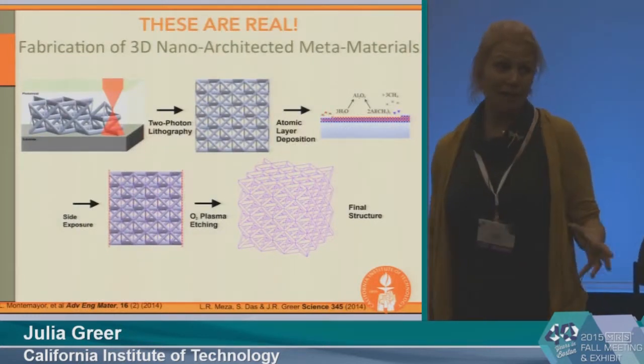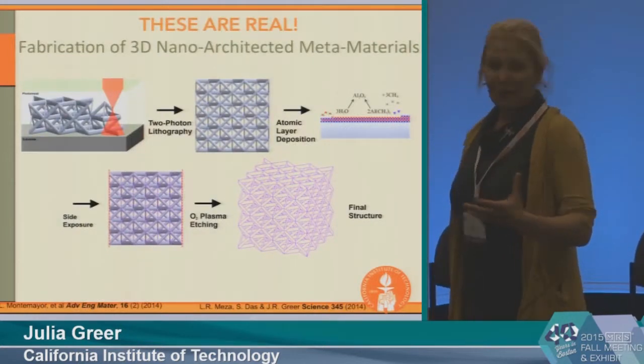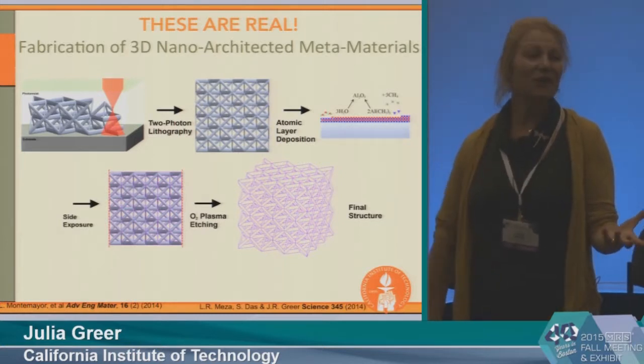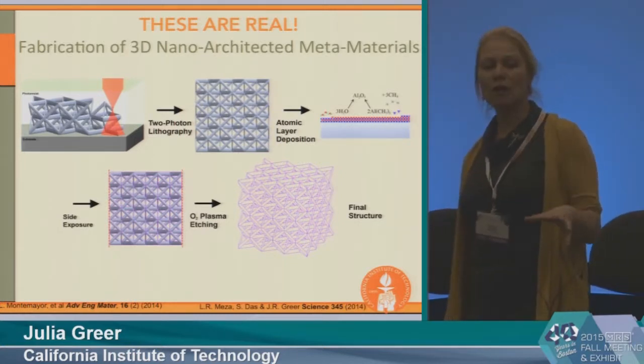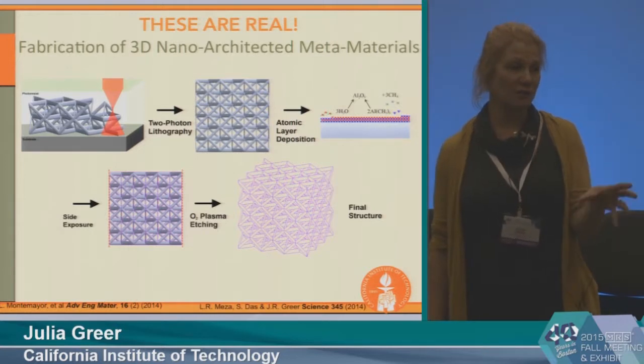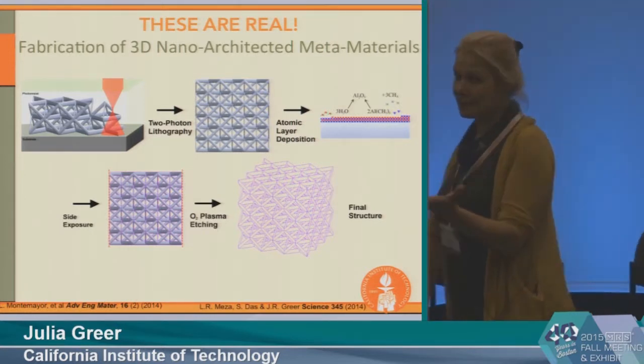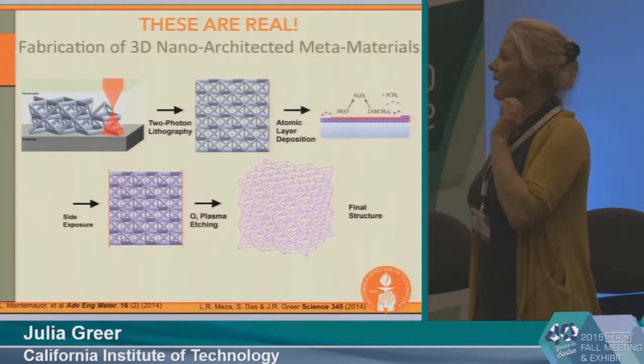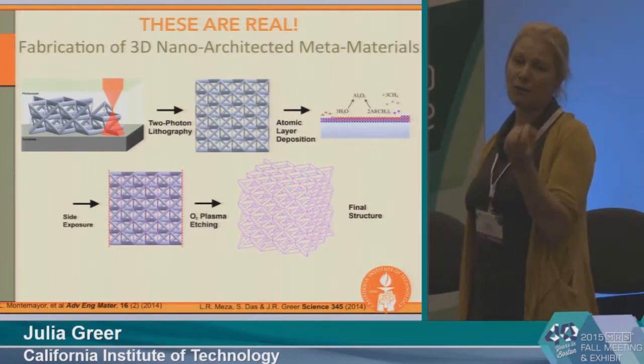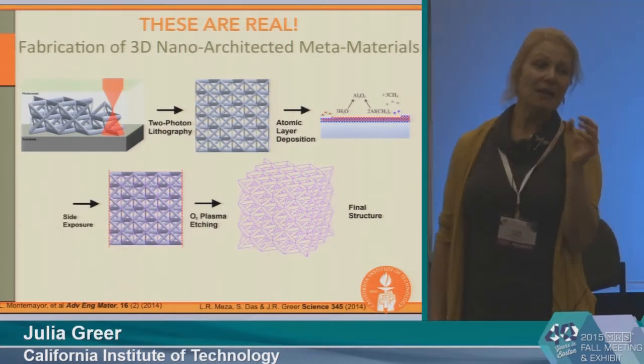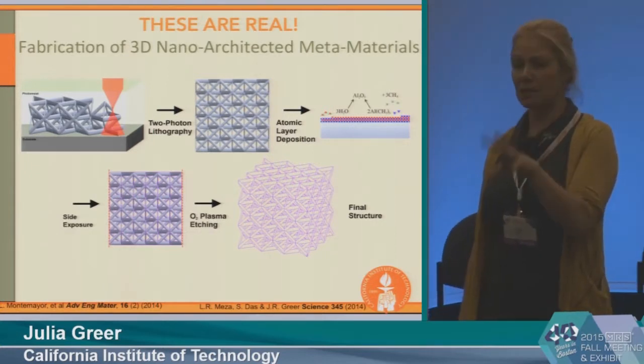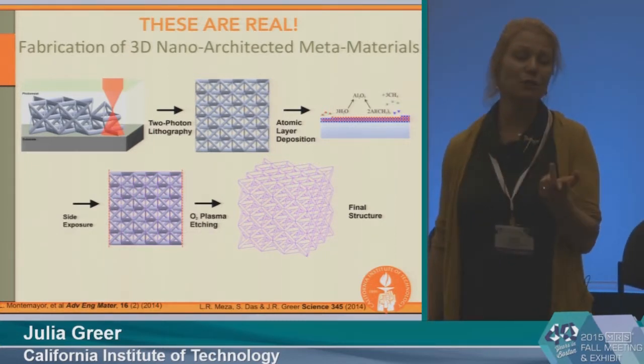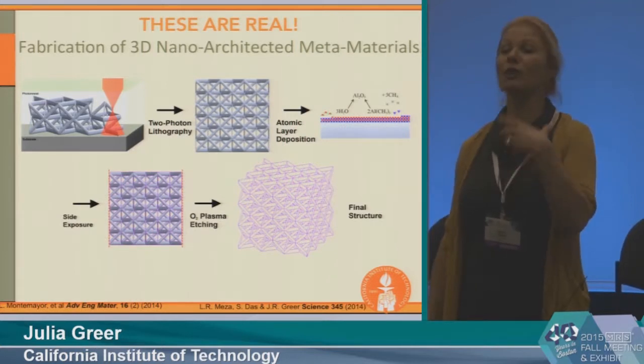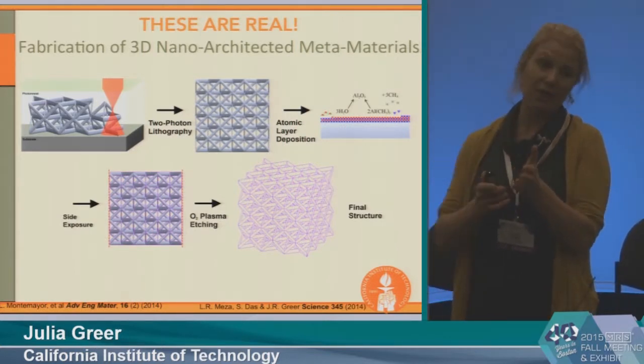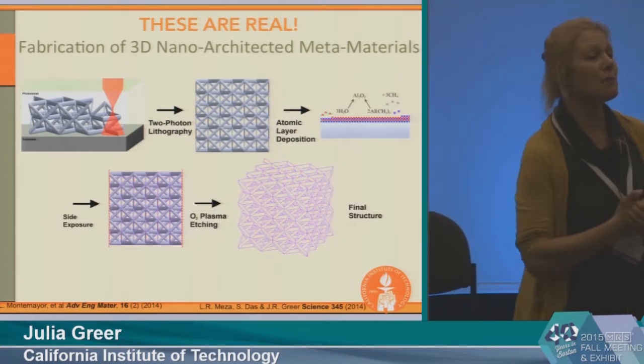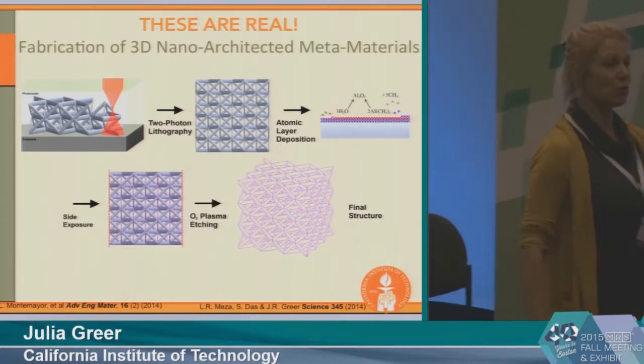So just a few words on how we make them, if any of you would like to know. We use a process called two-photon lithography to generate the original scaffold. The way it works is that it's a laser, and there's a photosensitive polymer, and when the laser interacts with the polymer, it forms a voxel. It's an interaction volume in 3 dimensions, and within that volume, with each single laser pulse, it releases exactly 2 photons. And the 2 photons, first of all, allow you to get the resolution down to these nanometer levels. And also they provide a sufficient amount of power to cross-link the polymer just within that voxel.